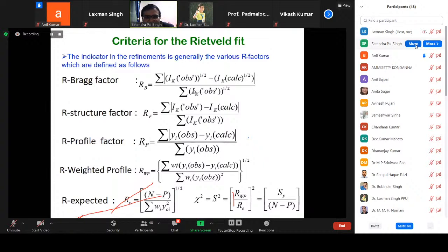Similarly, we calculate the R structure factor, the R profile factor, the R weighted profile factor, and R expected. Having these parameters, we look at a deciding parameter, the chi-square, sometimes also called S square, which is given by Rwp over Re. What is Rwp? It is the weighted profile, and Re is the expected value. N is the number of points, P is the number of refined parameters, Yoi is the observed intensity and w is the weight. So all these parameters need to be verified to confirm the validity of your refinement.